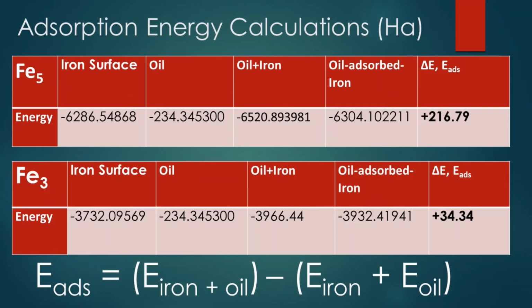The energy of adsorption is calculated as the energy of the iron surface and oil together minus the energy of the two molecules alone. The calculated adsorption energy for the iron 5 and iron 3 systems were about 217 and 34 positive Hartree, respectively. This indicates a large barrier to adsorption, although much less so for the iron 3 case. Obviously, these numbers are pretty large, but that's why I say the qualitative story is more important than the quantitative one.